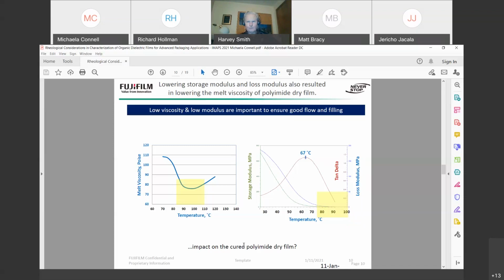However, as I mentioned previously, we must also look at the impact of altering the rheological properties on the other properties of the film. Such low storage modulus is unacceptable for the mechanical integrity of the film. So we then looked at the impact on the cured dry film of adding these diluents.